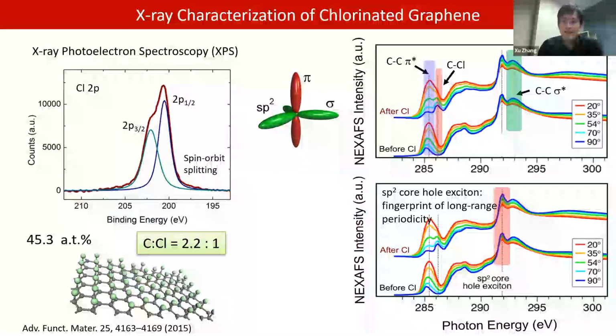Angle dependence analysis also reveals a lot of new features that are different from conventional 3D materials. Most importantly, we also see that the sp2 core hole peak does not change much after chlorination. That is a fingerprint of long-range periodicity of graphene. You can only see it in very high quality samples.